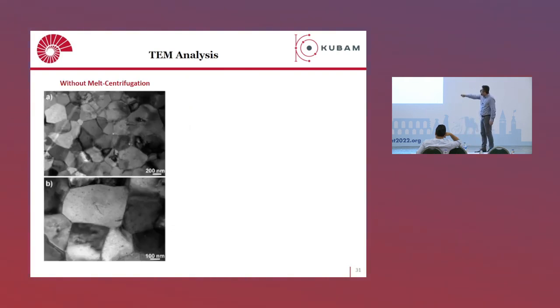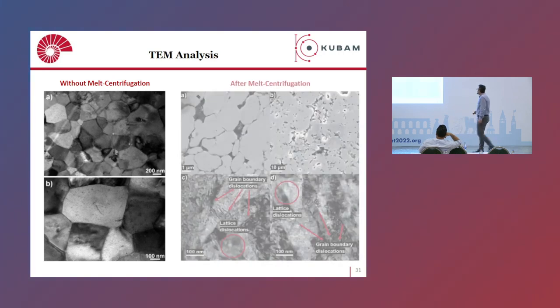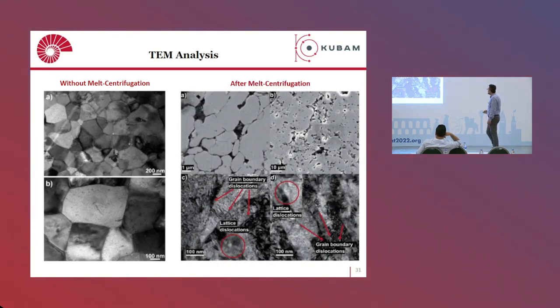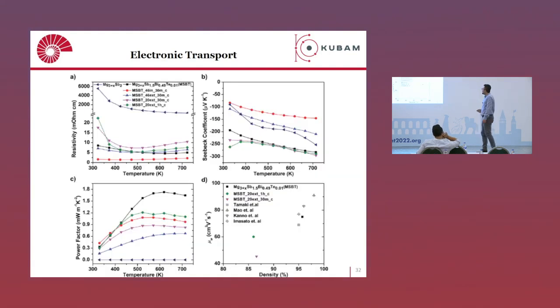So this is the microstructure with TEM without melt centrifugation. You can see a highly condensed, regular microstructure, let's say. And you can see that the average grain size is a couple of 100 nanometers. What happens if we apply this melt centrifugation? We create large pores, as you can see here, but at the same time small pores, which means microscale pores or nanoscale pores. At the same time, we create these disordered grain boundaries. They are nicely ordered, right? It is completely different than these grain boundaries. Plus, we also show some lattice dislocations within these grains. And we hope that this substantially reduces the thermal conductivity.